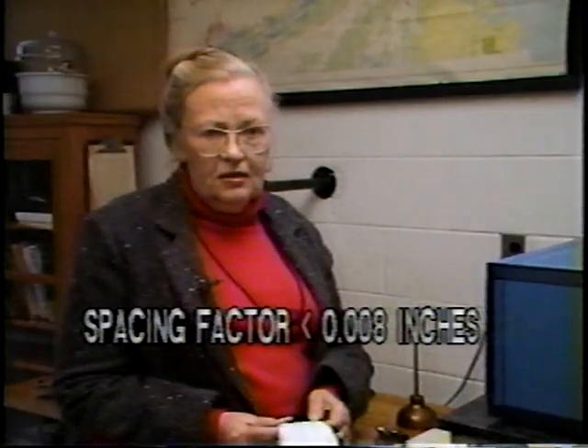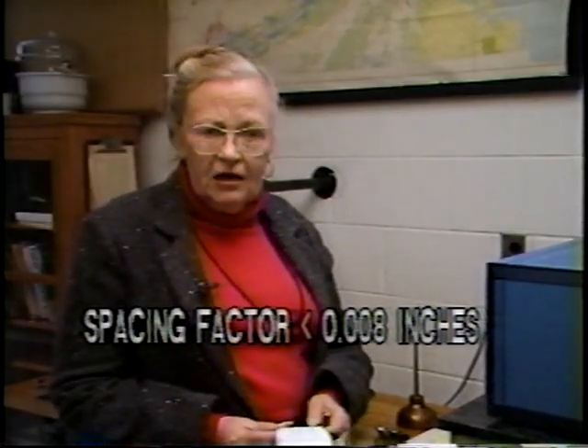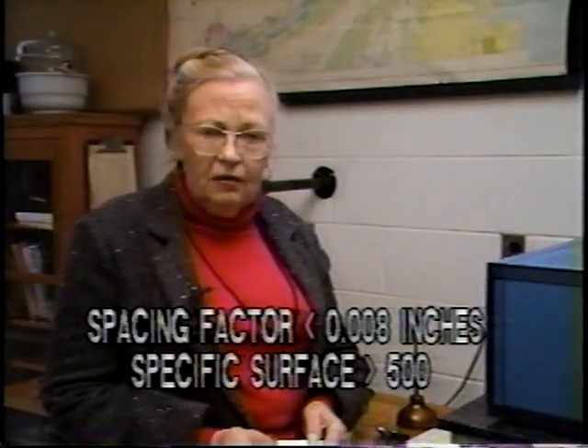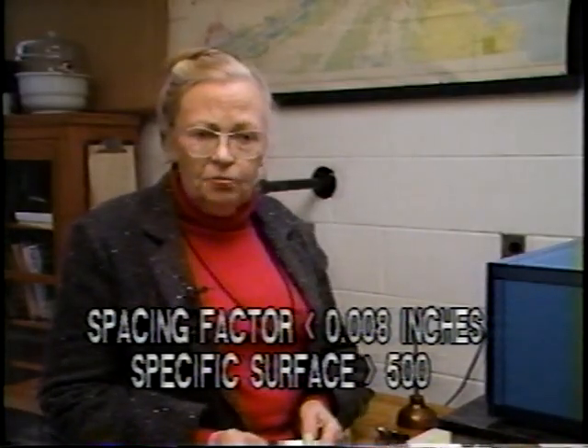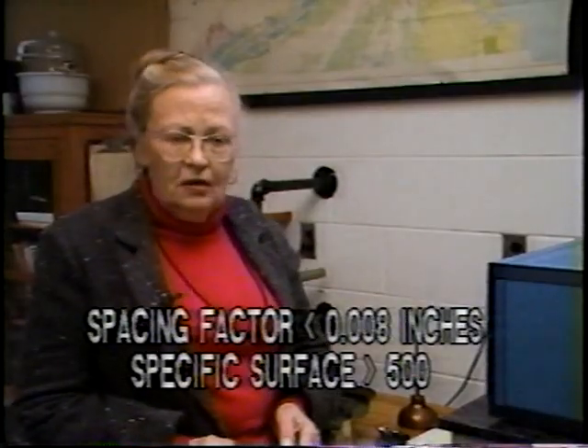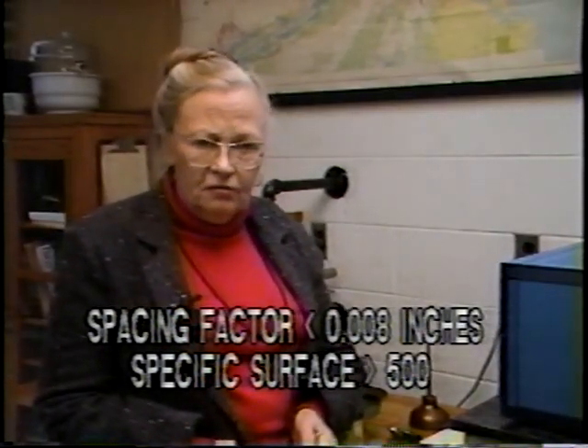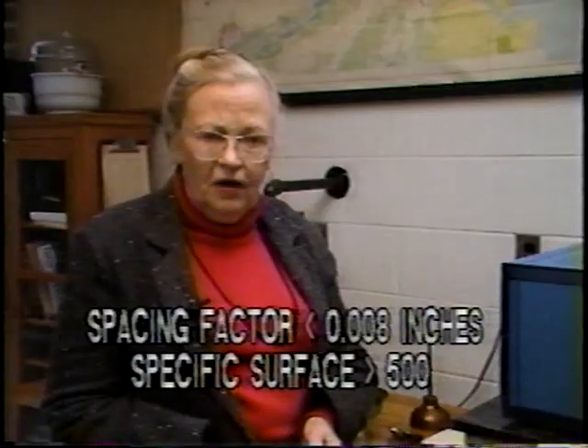Now about the data that comes out of the real linear traverse. We can calculate not only the percent voids, but also the distance between the voids and the average size of the voids. The distance between the voids is called the spacing factor, and it's a very small measure. 0.008 is the maximum. The specific surface is the measure of the size of the voids, and it's a reciprocal number, and it should be larger than 500. In order to provide protection against freeze-thaw deterioration, the spacing factor should be under 0.008, and the specific surface should be over 500.